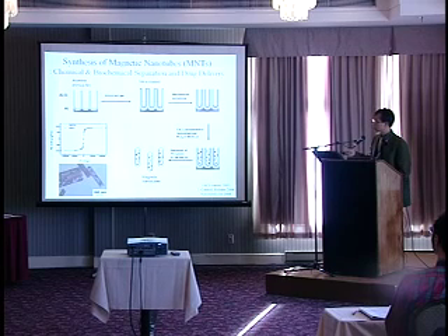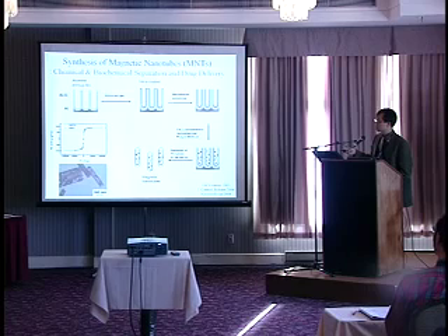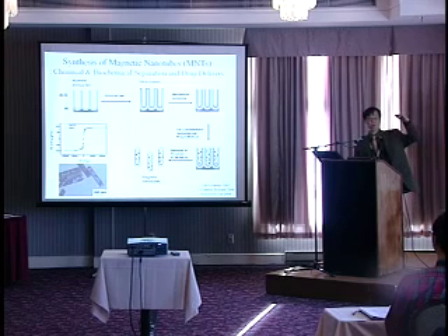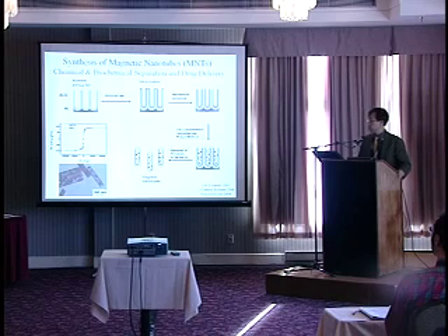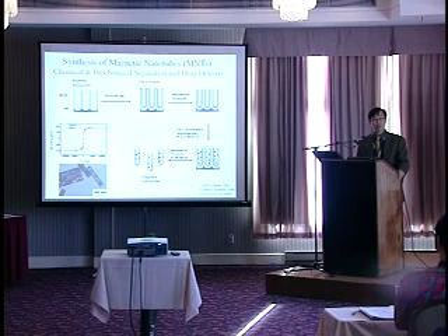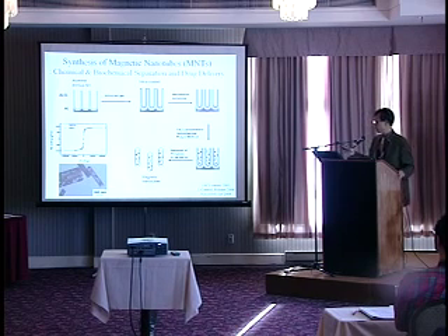And when you look at this SQUID data, you see an extremely high saturation magnetization value here, which is equivalent to bulk magnetic particles. In this case, the magnetic particle is magnetite. So there are not many groups who can achieve these bulk magnetic saturation values with magnetic particles.